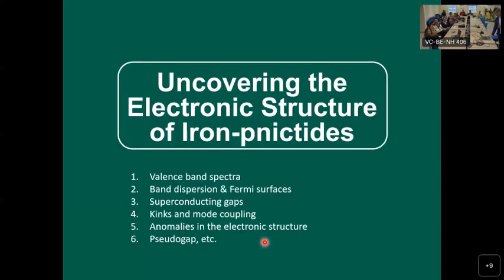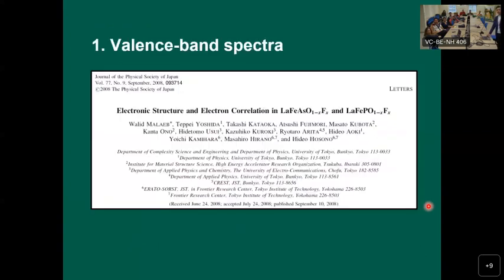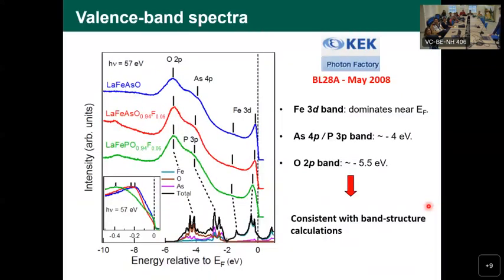Well, I just selected a few examples to show you how we really uncovered the electronic structure of iron pnictides using photoemission spectroscopy, starting with the first report. That was the first report we did on iron pnictides in 2008. Just to give you a brief idea here, we are interested in the electronic structure near the Fermi level, because these electrons are the main players, the contributors in superconductivity or some other exotic phenomena. Interestingly here, we noticed that iron, Fe 3d, was the dominant component near the Fermi level, which means that the name iron pnictides is very convenient. So, iron pnictides or iron-based superconductors.